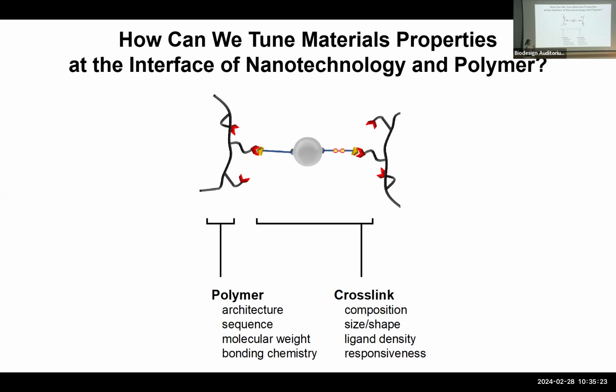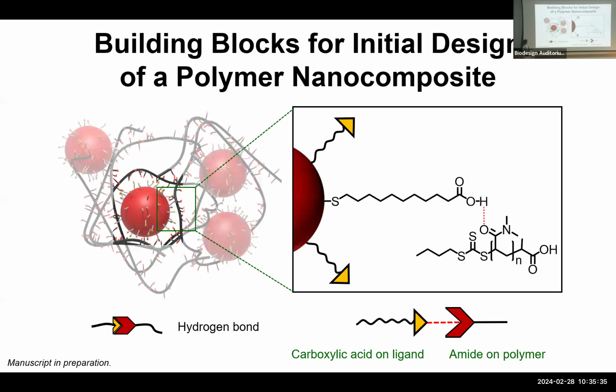We want to tune the number of binding events between the polymers and nanoparticles at the interface. Some of the preliminary results demonstrate that this is very important in controlling the bulk properties. The first step that we took was using a non-dynamic polymer that doesn't have any non-covalent interactions. It's a linear polymer. But by adding these nanoparticles that are functionalized with short ligands with carboxylic acids, we are introducing non-covalent hydrogen bonding interactions between polymers and nanoparticles.